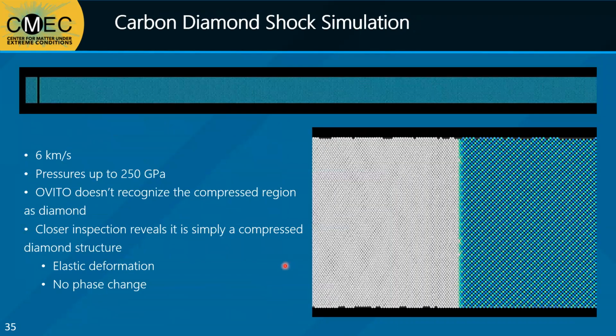I also ran some additional diamond simulations at higher piston velocities and pressures to see if amorphization could be captured in diamond. However, the Tersoff potential is not well fit for these conditions, so results may not accurately reflect what actually happens to shock diamond. Nevertheless, there are some things that can be learned or compared with experimental data to see what could be improved in the future. At these speeds, the simulation time steps had to be slowed down as we start encountering errors in atomistic collision, resulting in longer simulation times.